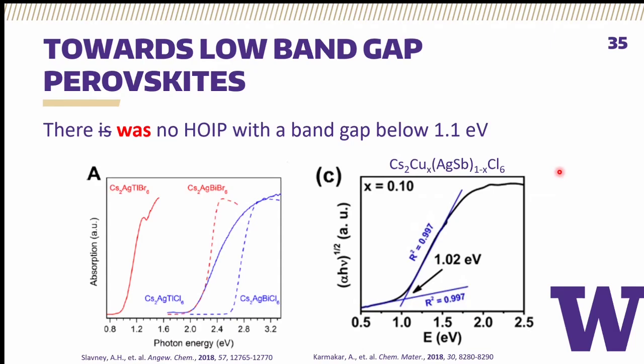Of the 2 to 4 materials that were identified, we wanted to focus on cesium silver thallium bromide because A, it was a direct gap material, B, it had a band gap of below 1 eV, the only material that had such a low band gap, and C, it didn't rely on these dopant additives, these inorganic additives, to reduce the band gap.